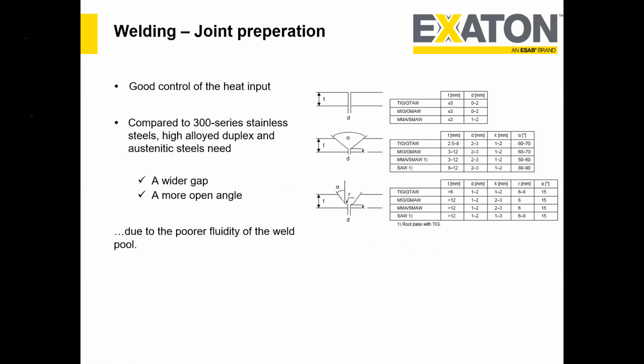For welding duplex, there are a few very critical things, which are basically thumb rules for how to avoid welding defects. Compared to stainless 316L, we recommend going for a wider root gap. A wider root gap helps two things. One, the welder has better access to penetrate the root. Another is that you should try to make the root pass or the weld metal by melting the filler metal more than the base material, because the base material has a lower amount of nitrogen, and if we melt more of the base material, it will evaporate the nitrogen, so there will be a depletion of nitrogen.